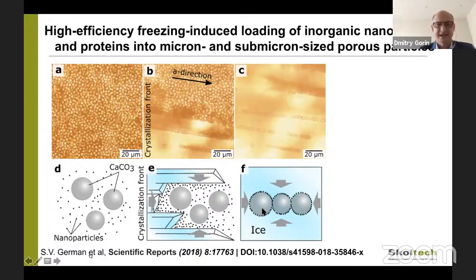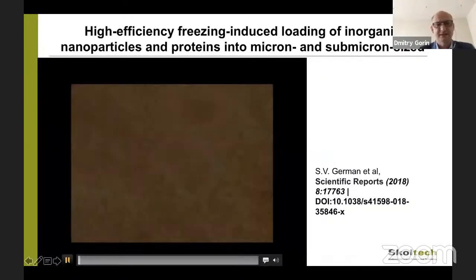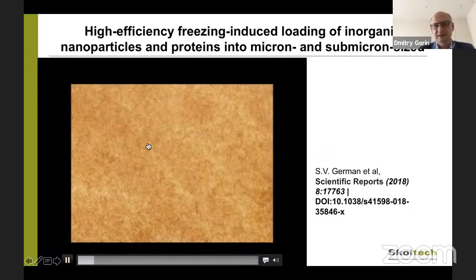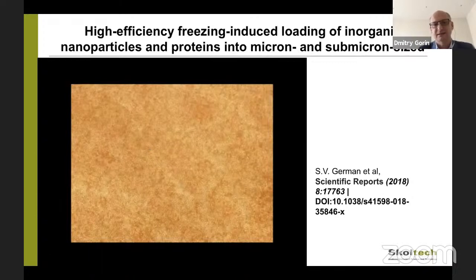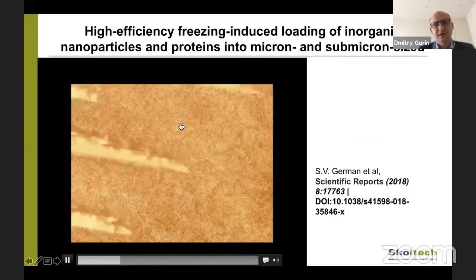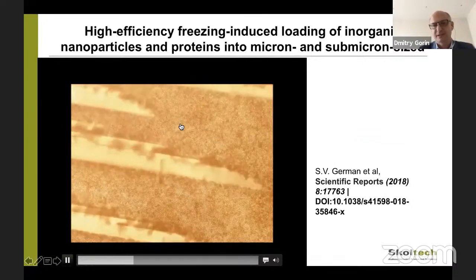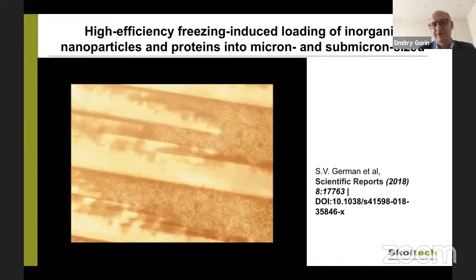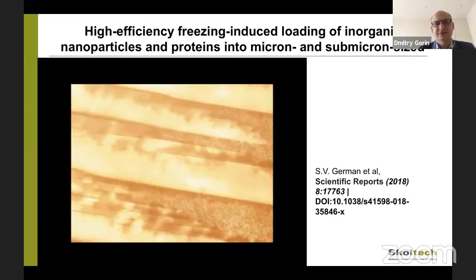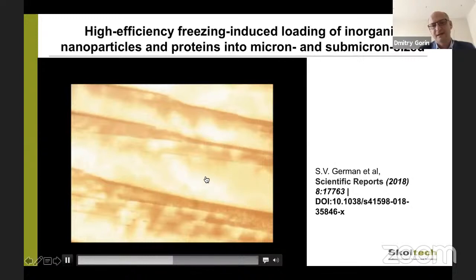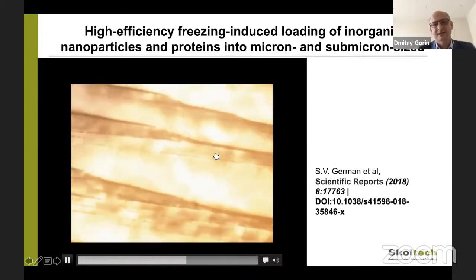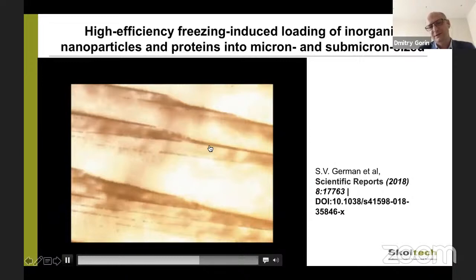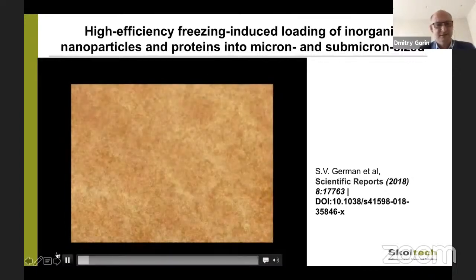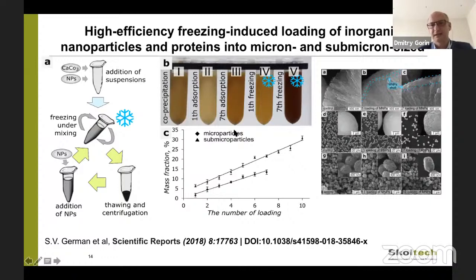carbonate particles. And how does it look in reality? The brown color is magnetite nanoparticles with a size of 10 nanometers, and the white particles are calcium carbonate particles with a size of 3-5 micrometers. And you see formation of ice crystals, and as a result we induced adsorption of magnetite nanoparticles on the surface of calcium carbonate particles. And then you can see how it looks.